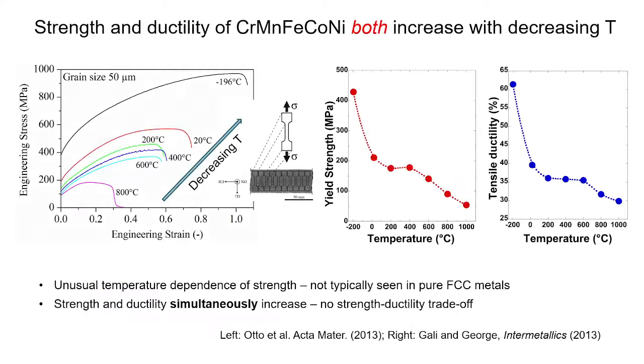So the one unusual thing about FCC HEAs is that both the strength and the ductility increase with decreasing temperature. In steels, for example, we all know the experiment that we do in undergraduate labs where we take a sharp impact bar and put it in liquid nitrogen and hit it, and it breaks like glass. But these FCC HEAs get stronger, but they also get more ductile as you decrease the temperature. So this is the strength, this is the ductility, and both of them increase with decreasing temperature, which is an unusual, good combination to have.